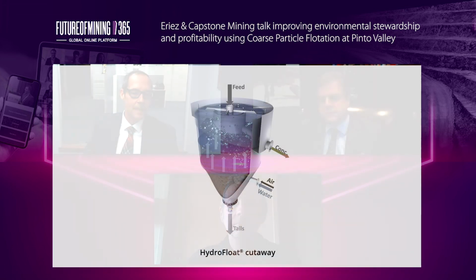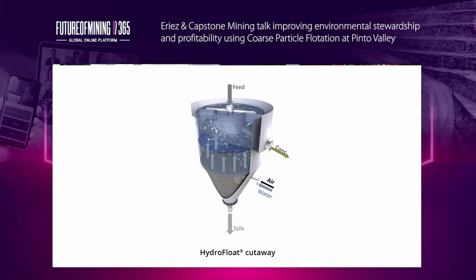By comparison, the HydroFloat, which you're showing now, does not use an impeller. It uses a liquid fluidized bed, which is much more efficient for particle contacting. And also there's less wasted energy that ends up causing the bubbles and particles to detach before they get to the overflow. Also, from a contacting perspective, the HydroFloat uses countercurrent flow, which is more efficient and creates less short circuiting than a stirred tank. And that's why you don't need to put HydroFloats in series as you do for conventional stirred tank flotation cells.